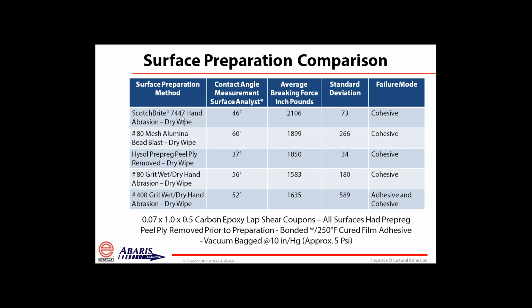However, when you look at the Scotch-Brite and the bead blast versus the peel ply, and this is a Hysol prepreg peel ply that we use, versus an 80 grit wet dry abrasive, aluminum oxide, another 400 grit wet dry abrasive, you can see that you get a range of different contact angle measurements from the surface analyst. The lowest number in that matrix, the lowest contact angle, actually exists when you pull the fresh Hysol prepreg peel ply off of the surface, but it doesn't extrapolate to the highest breaking force.